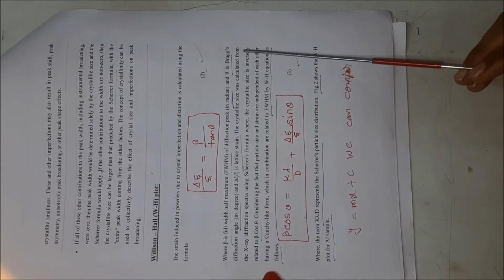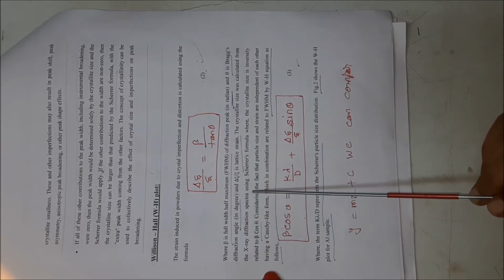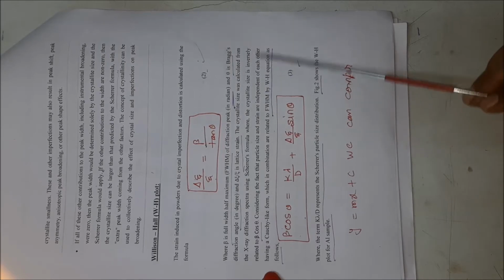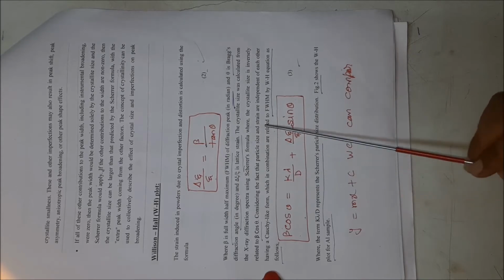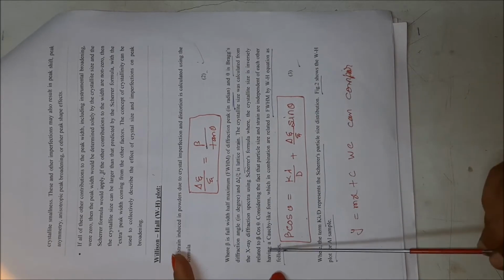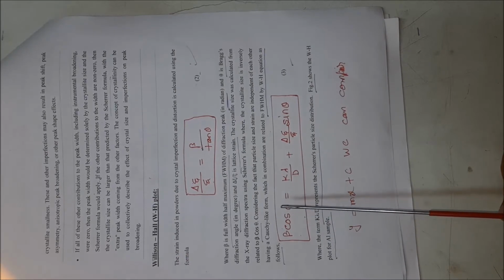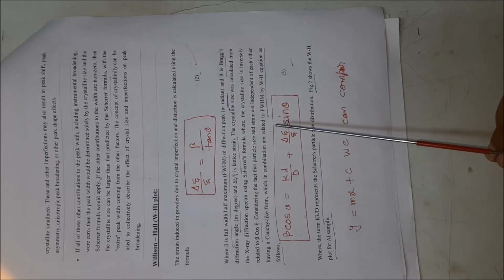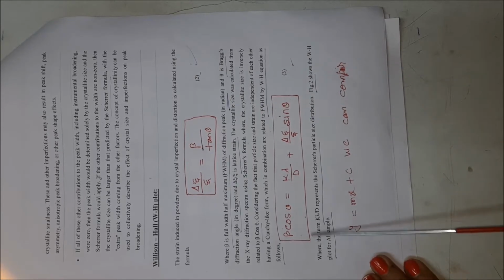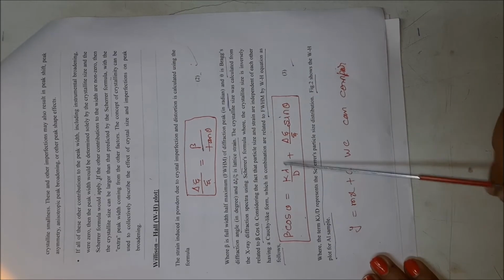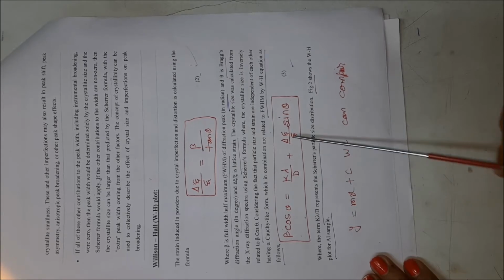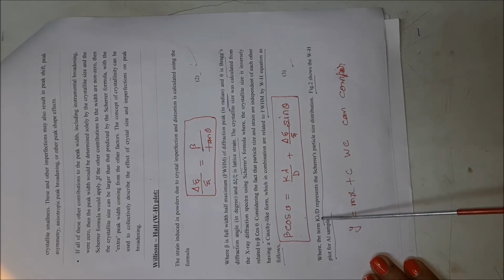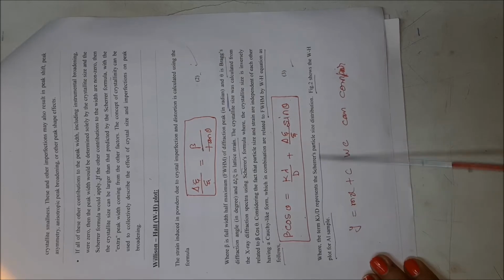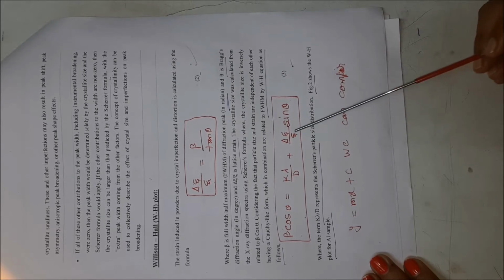Now, the crystallite size was calculated from the X-ray diffraction spectra using the Scherrer formula, where the crystallite size is inversely proportional to beta cos theta, and considering the fact that particle size and strain are independent of each other, having a Cauchy-like form, the combination is related to FWHM by the WH equation as follows: beta cos theta equals k lambda upon d plus delta d upon d sin theta, where k lambda upon d represents the Scherrer particle size and delta d upon d is the lattice strain.